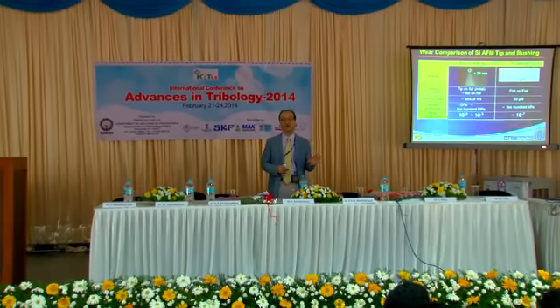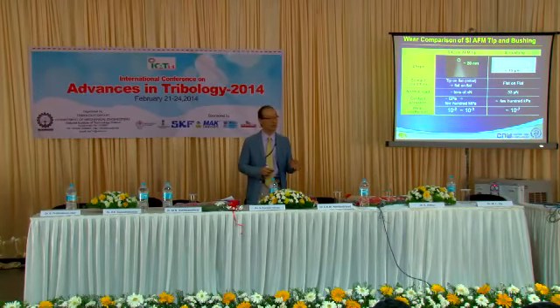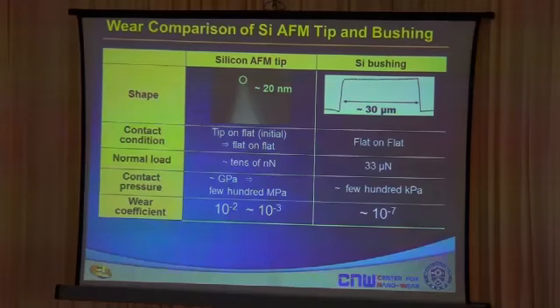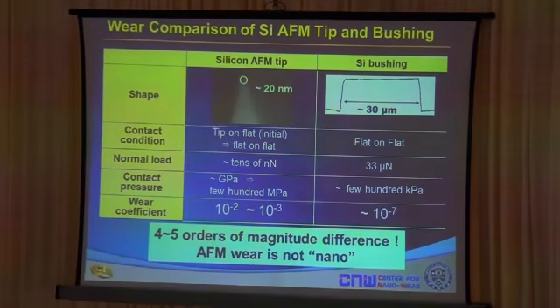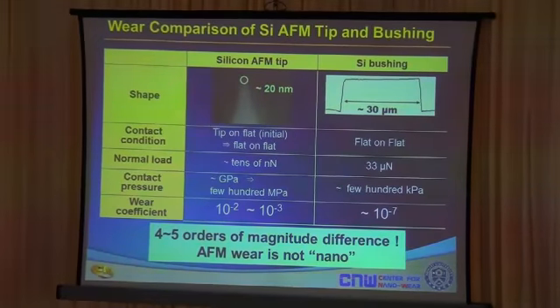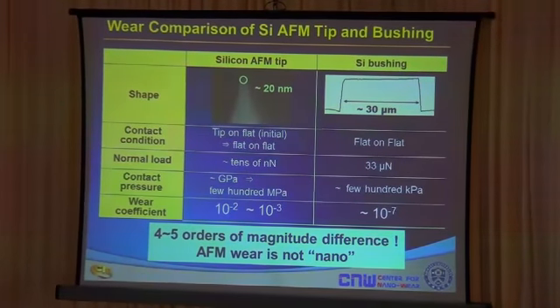So basically, what this study is showing you is that, again, tribology is very system dependent. It's not a material property. Depending on the contact condition and also on the contact pressure, you can have tremendous difference in the tribological characteristics. There's 4 to 5 orders of magnitude difference, and AFM wear certainly is not at the nano level. It's tremendous if you quantify it.